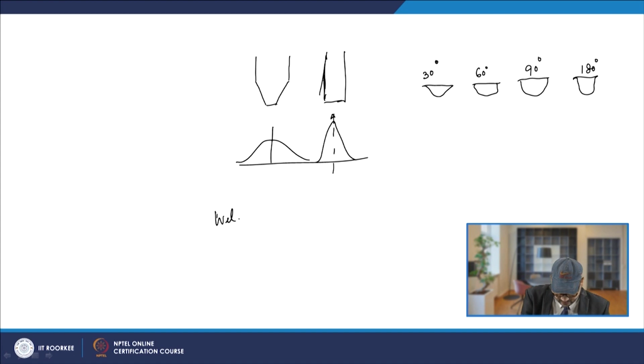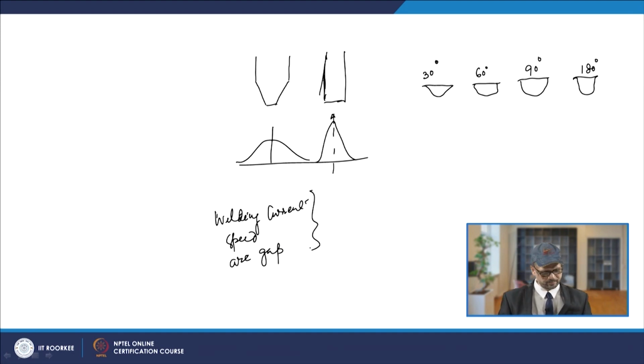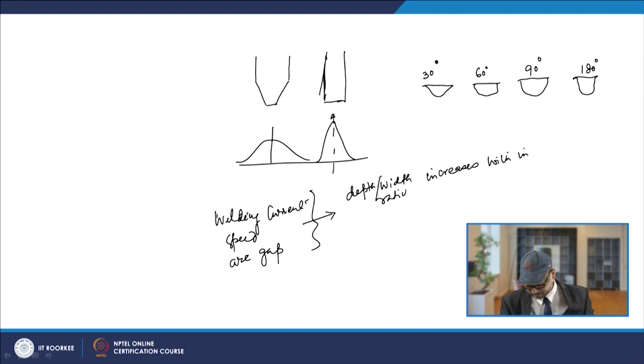This observation was made by one of the researchers, Savage, and he found that if you keep the welding current, the speed and the arc gap constant, then the depth by width ratio, this is the depth upon width ratio, increases with increasing vertex angle of the conical tip of the tungsten electrode.